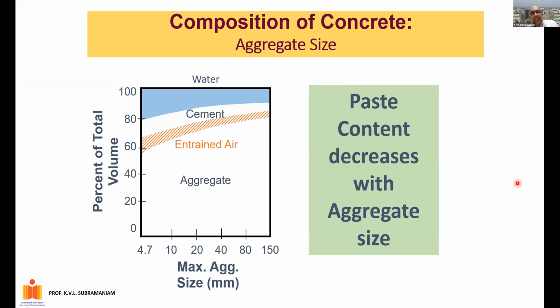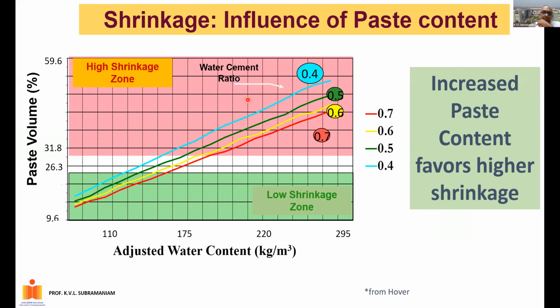Now, this requires going back to the drawing board, trying to understand what causes shrinkage. Shrinkage is produced by the paste. And now going back to the basic engineering, we need to understand packing. So we understand that when I increase the aggregate size, my paste content decreases, so the shrinkage would decrease. And the paste content plays a critical role.